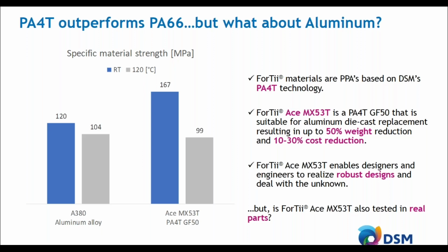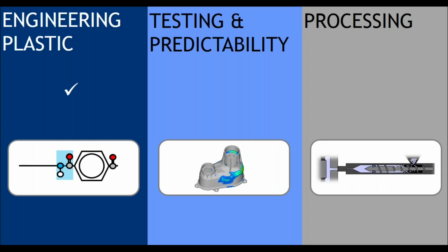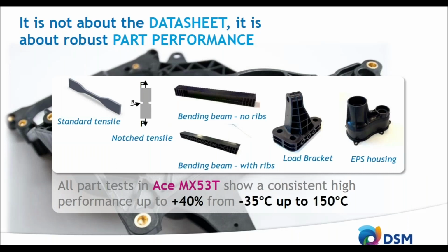Question, of course, this is all nice, but is it also tested in real parts? And there we want to show you a bit on how we design at DSM. So some testing and some predictability. We know it's not about the datasheet, it's all about the part performance. And that's also why we do not design our materials based on a standard tensile bar or a notch tensile bar. But we make parts like bending beams, load brackets, EPS housings, and we test them extensively to see how the materials behave under static load conditions, but also under fatigue conditions during the lifetime of your part. What we see is that with ACE MX53T, we have a consistently higher performance of up to 40% compared to other PPAs from minus 35 degrees up to 150 degrees C.